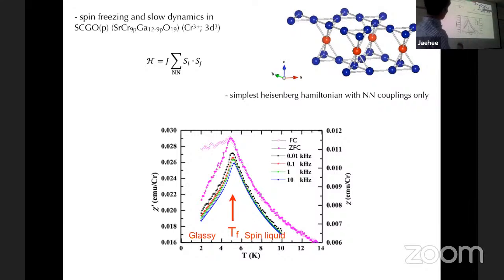Okay, and now going to the physical chemistry, the chromium 3+ ion has 3 electrons in t2g levels, and each chromium ion is surrounded by 6 oxygens octahedrally, and neighboring chromium ions share 3 oxygens. So direct exchange interaction between these neighboring t2g electrons dominates the interactions. So basically, the spin Hamiltonian is the antiferromagnetic nearest-neighbor interaction only, and the further neighbor interactions are negligible. And there's no single-ion anisotropy term because chromium 3+ ions have quenched angular momentum. All right. So in fact, it realizes experimentally a very nice simplistic, frustrated spin Hamiltonian.